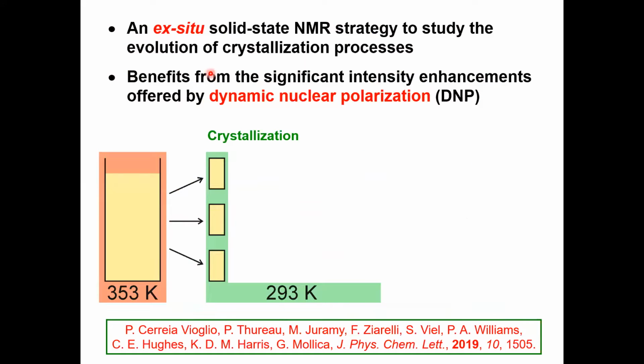So this is an ex situ study of the evolution of crystallization. And as I say, the objective is to benefit from the intensity enhancements from dynamic nuclear polarization. One of the motivations here is to be able to study the very early stages of crystallization where the amount of the solid form is very low. But secondly, to allow us to carry out more sophisticated NMR measurements, maybe two-dimensional NMR measurements, which we cannot do in the time scale of the in situ studies I described earlier.